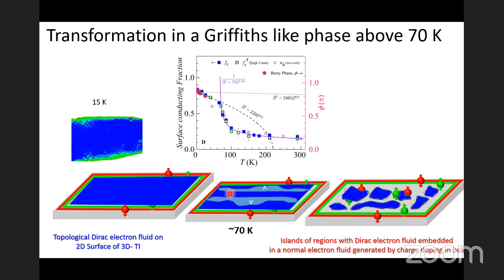We don't know how they interact, but we feel that the breaking of the system from this uniform 2D surface state to this patchy network happens exactly where the bulk electrons are being excited in the bulk of the system, generated by disorder. And because of this, the transition temperature is different from the bulk transition temperature at 70 Kelvin.